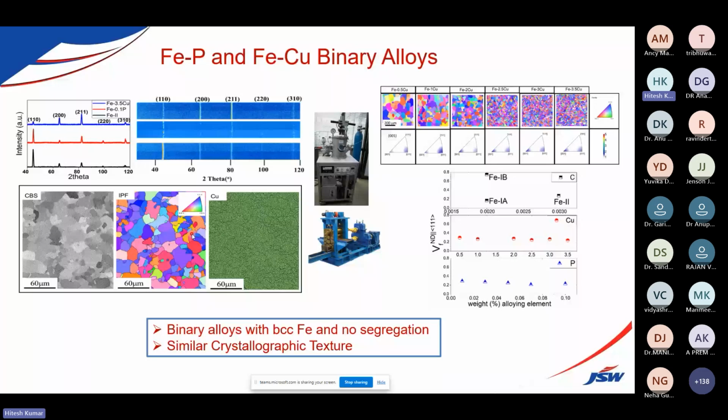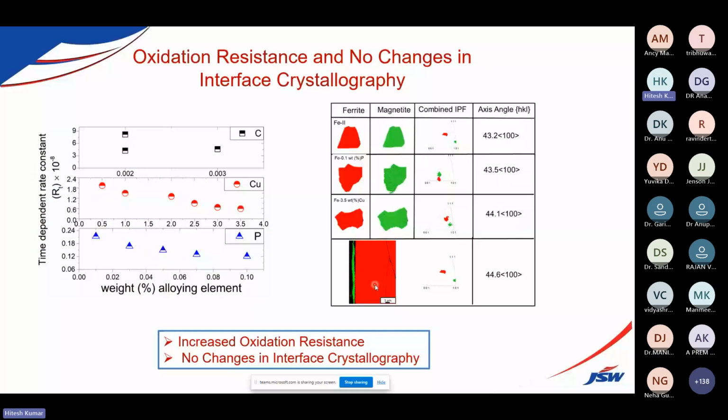These are the XRD data which we calculated, which later help to find out the residual stress inside our material. To confirm, we tried to find out whether there is a homoepitaxy or heteroepitaxy change by adding alloying elements. We observed there are no major changes in the epitaxial growth.